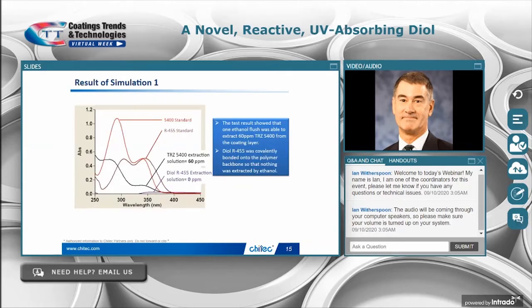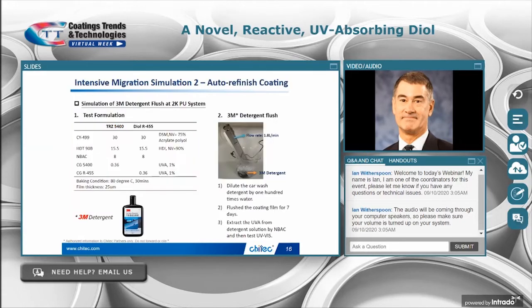Okay. And then the extracts were analyzed by UV spectroscopy, and they clearly show that much more 5400 was extracted than R455. Essentially, no diol R455 could be detected. We're getting down into the noise levels there using this ethanol-water extract. So this reinforces our position that the R455 is tied down pretty well, and that the other UVAs can be extracted. Even a triazine can be extracted, which is a bigger molecule.